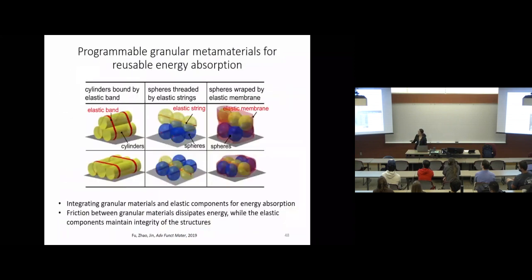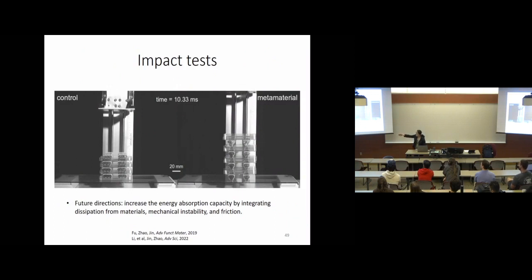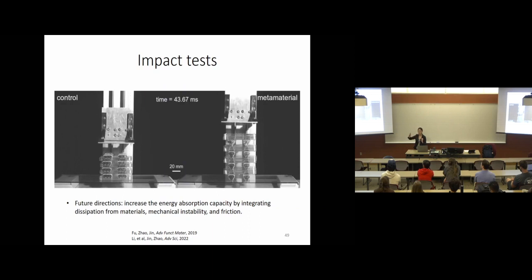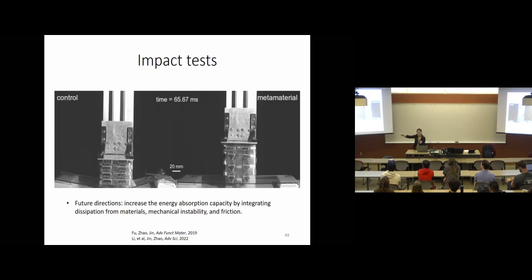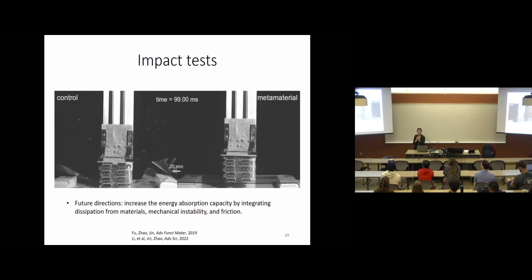But in our recent paper, which I didn't have time to talk about, for the number on that slide I showed you, this is like 3 or 4 magnitudes lower than what is needed compared to traditional material. But in this paper, we indeed increase that number to that level. Mainly how we achieve it is friction here. This is a very low density, but if you increase the area for friction, then you can potentially increase the number. And moreover, if you combine the different mechanisms together, you can also increase the number. So here the friction plays a more important role to dissipate the energy, compared to the snapping with additive absorption, right?